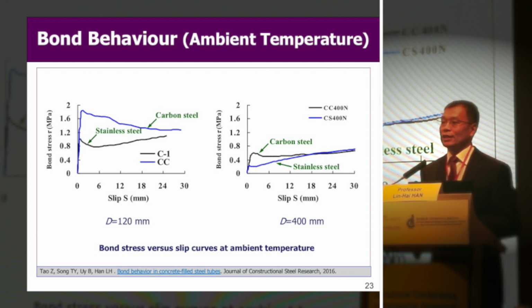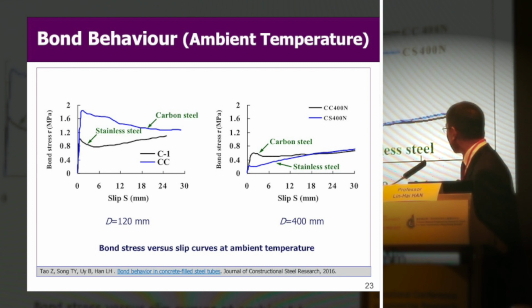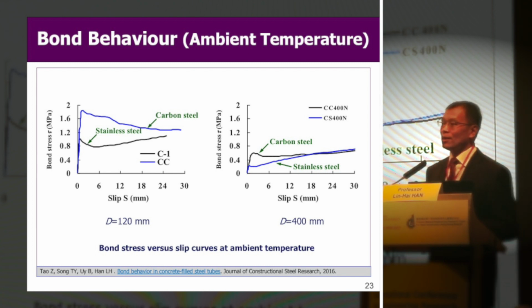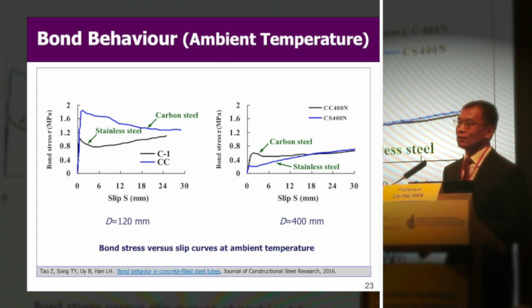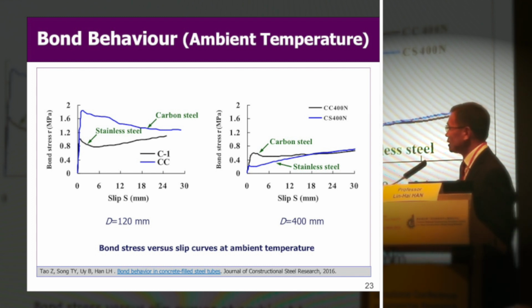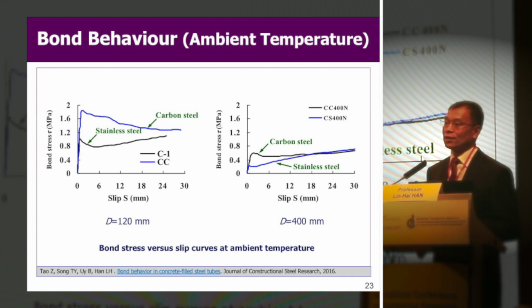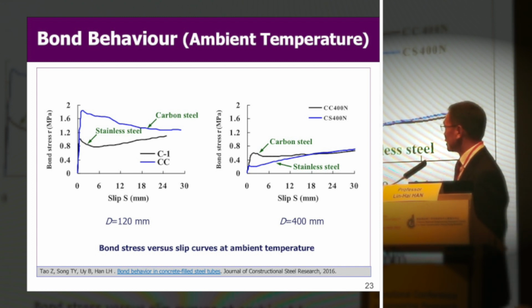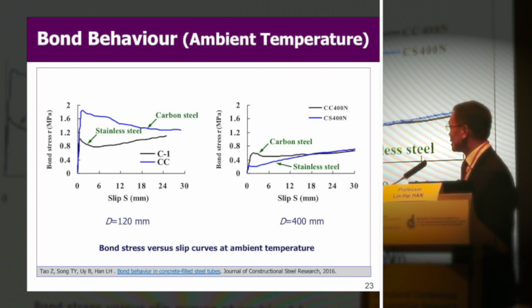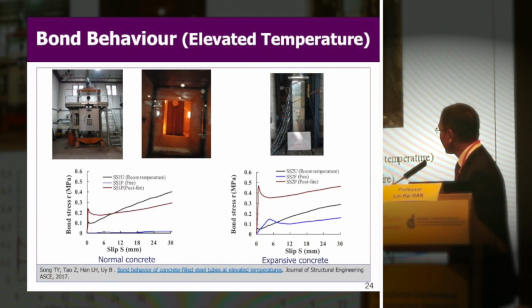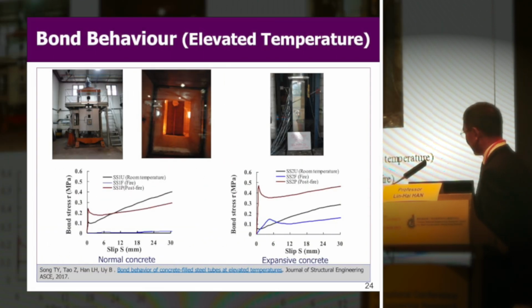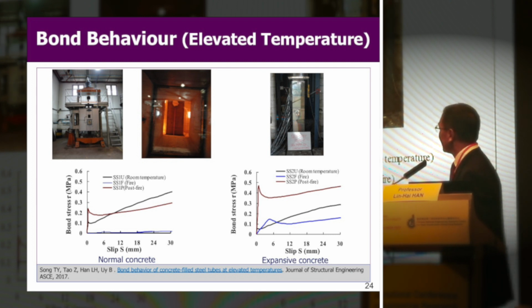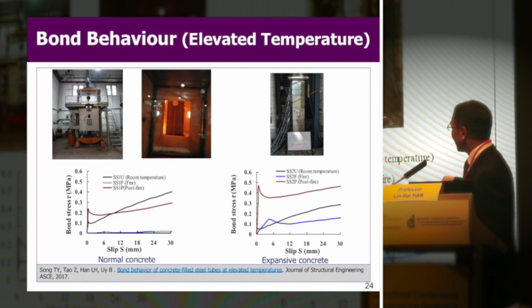Different characteristics. But the bond strength changes as the loading process goes. Actually, this is because the microstructures of the concrete and the outer steel tube change a lot during the loading process, compared between the two types of steel tubes. And we have also checked the bond behavior at elevated temperature. That's the type of test like that.